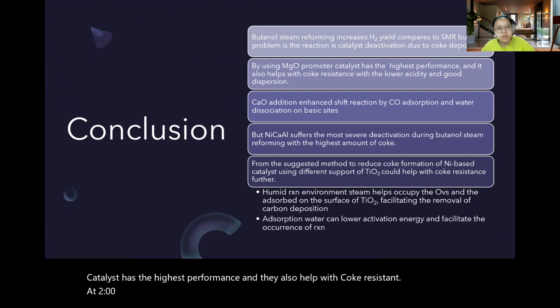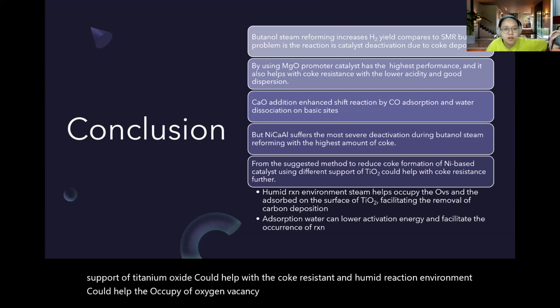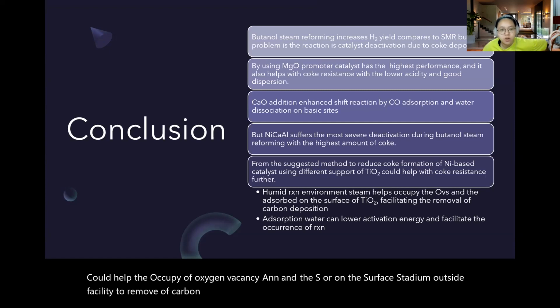To further reduce coke formation, I suggest trying a nickel-based catalyst using titanium oxide as the support, which could help with coke resistance. A humid reaction environment could help occupy oxygen vacancies, and the water adsorbed on the surface of titanium oxide facilitates the removal of carbon deposition. Adsorbed water can also lower the activation energy and facilitate the reaction.